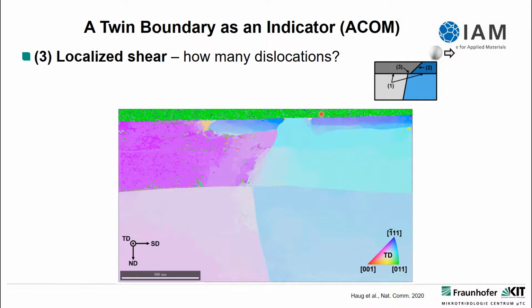That's the electron beam deposited platinum, used to protect the surface, or the entire material, from beam damage while cutting the TEM foil. What we do see is different colors to the right and left of the twin boundary, and also here where this lower dislocation trace line is, there's a change in color from below to above.